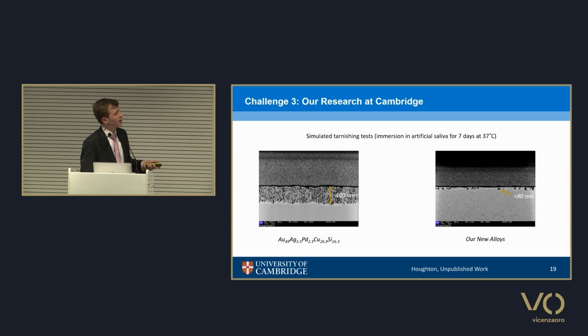So as you can see, this is using what we call a focused ion beam scanning electron microscope. For those of you that are more interested in the technical side of things, the magnification is 50,000 times and the working distance is 5.1 millimeters for both. So they're at the same scale. And as you can see in the Schroers alloy, we have a tarnishing depth of about 400 nanometers. And in our newly developed alloys, we're down to about 80 nanometers. So we're largely close to a commercially viable alloy.